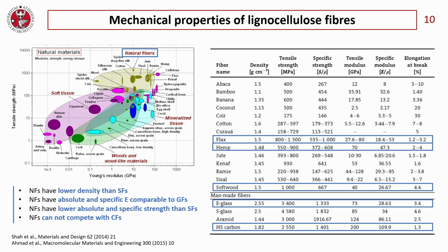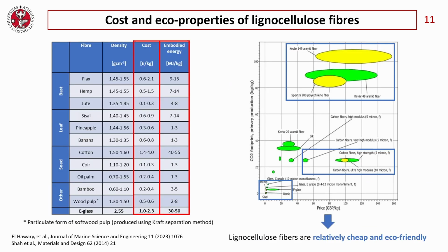tensile strength. But if you consider tensile modulus, we can see that the most important natural fibers can compete with the E-glass fiber. And they are also lighter. They are much lighter with respect to the man-made fibers. So these natural fibers can be an important competitor for glass fiber, not for carbon fiber. This is the most important consequence.